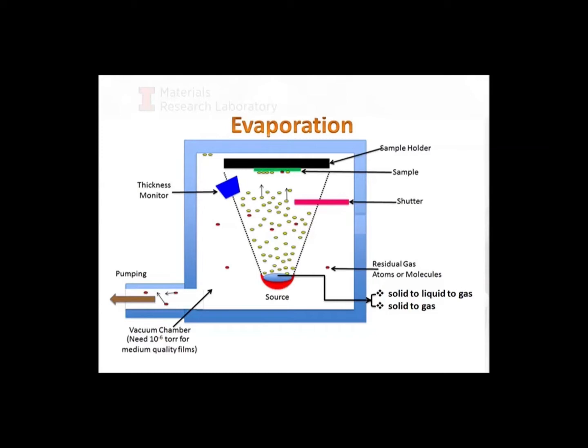Thermal evaporator works by passing current through a boat which contains source materials inside it. The source material will undergo a change from the solid state phase to the vapor phase by means of thermal heating. The evaporated atoms then travel in straight lines due to a long mean free path created by the vacuum, and then deposit on top of your sample, on top of your wafers.